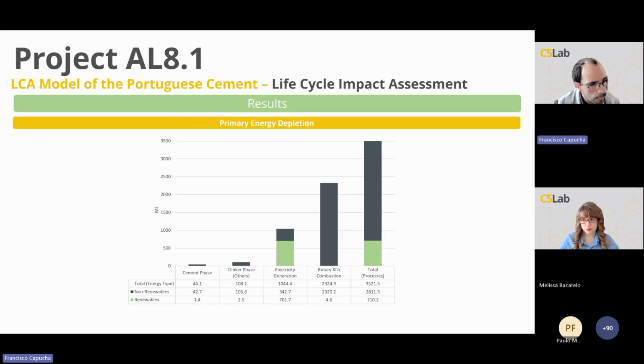The trend continues when analyzing the primary energy depletion, where it's possible to conclude that the rotary kiln depletes over 2.3 gigajoules of non-renewable energy. This model does not consider the procurement of alternative fuels, because due to the polluter pays principle, they are excluded from the model. This is then followed by the electricity generation, which depletes around 1 gigajoule. However, due to the high incidence of renewable energy in the Portuguese electricity mix, around 70% of it is considered renewable.